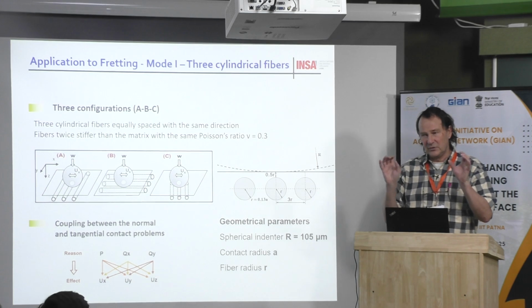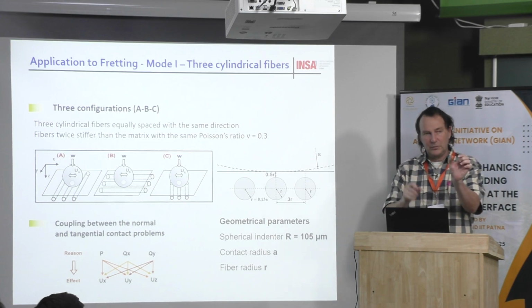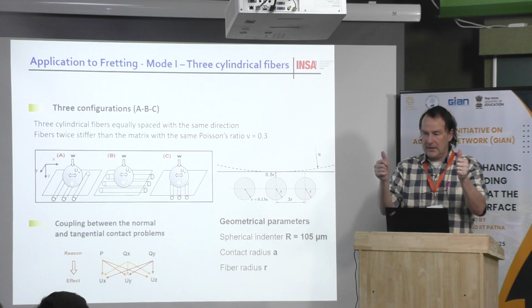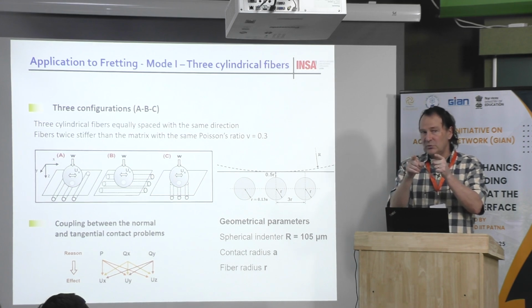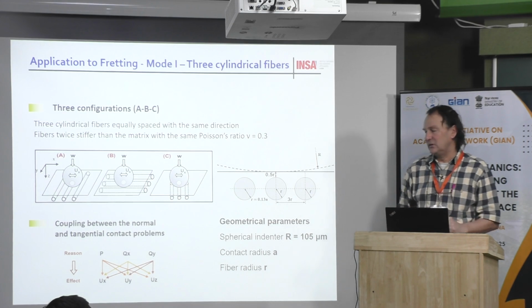Because when you consider the Eshelby theory with 2 close inclusions of radius 1, for example, if the gap between the 2 surfaces of the inclusions is 2, there's almost no effect. If it is 1, you start to see some effect. And if it is below 1, you will see more effect. This is a dimension that you have to keep in mind.